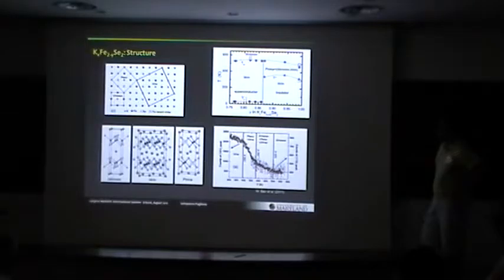So this is some neutron scattering data, and I believe this is structural. Yeah, these are structural peaks. And you can see that there are some different behaviors. Now this is one of the particular compounds, just as an example, to show you that there's some structural ordering that changes as you cool this thing down. And here's one of the nicer phase diagrams that has appeared, talking about mostly structure, but also the physical properties. You can see that this is a function of X, which is the potassium content, going from 1 downward. There's generally a structural transition up here that coincides with this magnetic ordering. And there can also be some intermediate structural transitions between these different vacancy-ordered symmetries. On this side, it seems, at least in this study, that the superconducting compounds do not have this intermediate structural transition. Very strange.